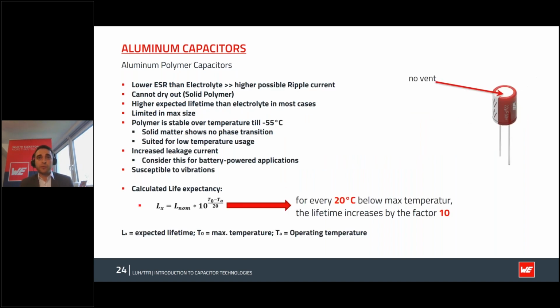The other technology is aluminum polymer types, a little bit newer, and it provides advantages when it comes to the ESR as it has a lower one. It cannot dry out as it has a solid in it and no liquid. It has a better expected lifetime. However, the size is limited. It's very stable over temperature as there's no phase transition, so the electrolyte cannot freeze or the polymer cannot freeze or vaporize. You see, they won't have a vent as it's not necessary because they have no failure mode which would explode like the electrolyte. They do have, however, increased leakage currents, which you have to consider if you want to have a battery powered application as it might drain your battery.